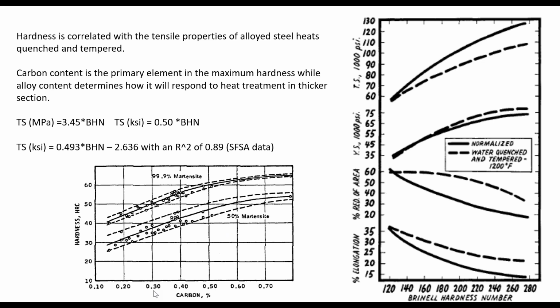Today, we don't want to make any steels that are over 0.3 because they'll crack. If you want a piece of jewelry or you want to pay us extra, we'll make a 4140 or 4340 or an 8640. But typically we only make up to about 8630, and our sweet spot is right here around 25 to 27. So most of our alloy steels are really in this range here. We have a few where we're worried about weldability where we go down to 15. We hate going below 15.